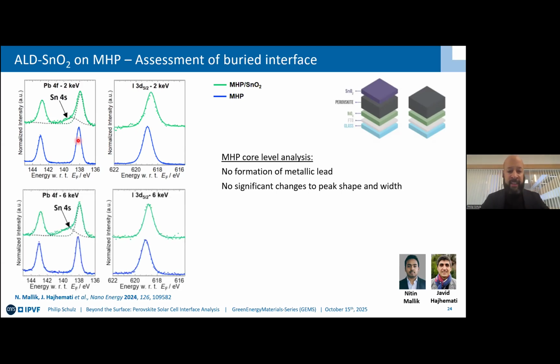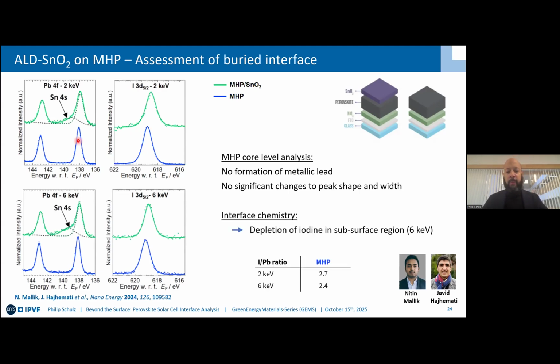Also looking at 6 keV, we get to a very similar picture. But once you actually go into the quantification, you can identify depletion of iodine in the subsurface region. It starts off with a stoichiometric ratio for the surface of the perovskite, and once you go to the subsurface, you see that they are slightly iodine deficient.